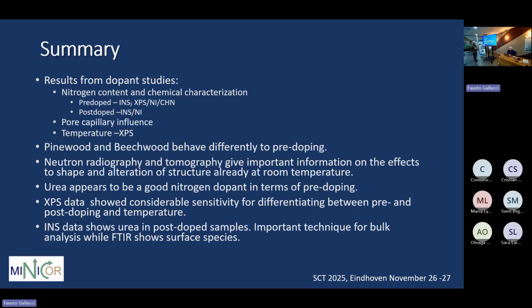Neutron radiography and tomography give important information on effects on shape and alteration of structure already at room temperature. Urea appears to be a good candidate as a nitrogen dopant in terms of pre-doping. And, as I said, XPS data showed considerable sensitivity for differentiating between pre- and post-doping and temperature.